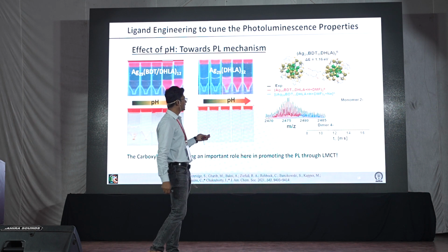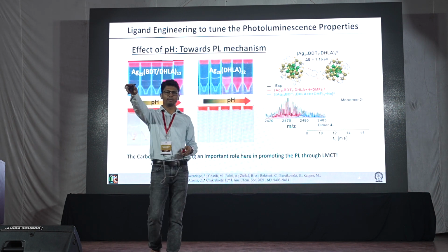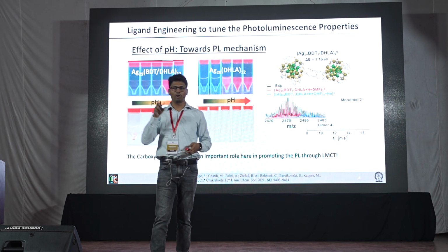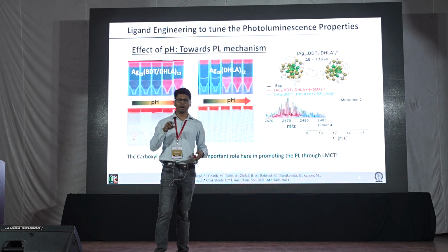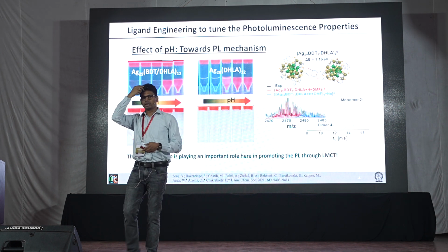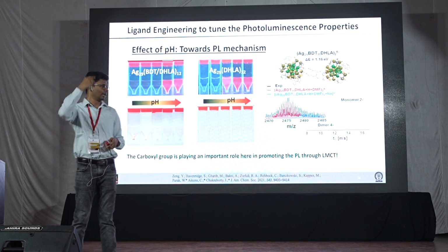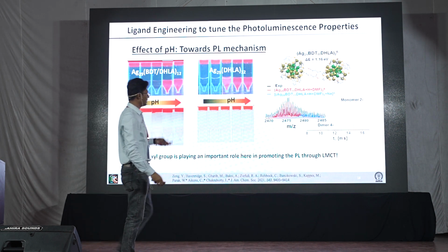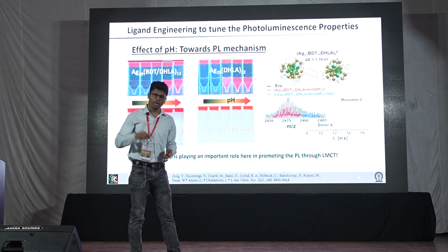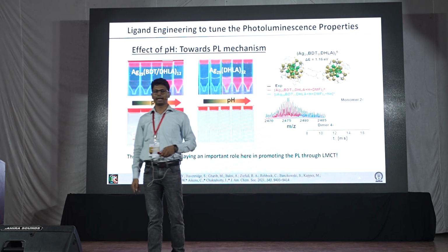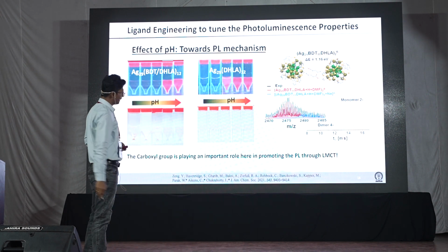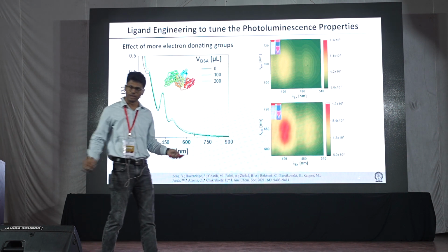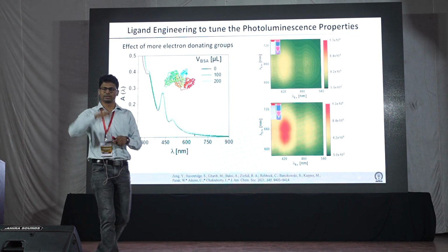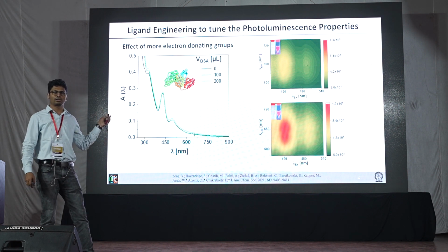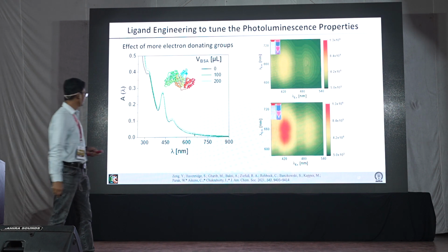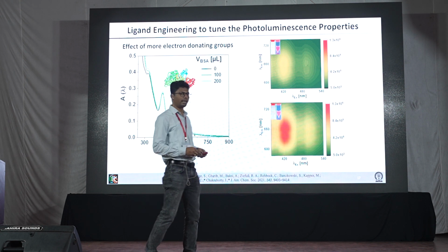But probably another possibility is this carboxyl group anchoring on the metal surface. So there is also the possibility of intra-cluster charge transfer from one carboxyl group to the other clusters. So that might also add up to this process. But nevertheless, we find that adding more and more carboxyl groups to the system can help a lot. We did a control experiment with polymers and proteins, which just adsorb on the surface and are not aggregated again. We have validated that. So if you add that kind of protein, that enhances it further.